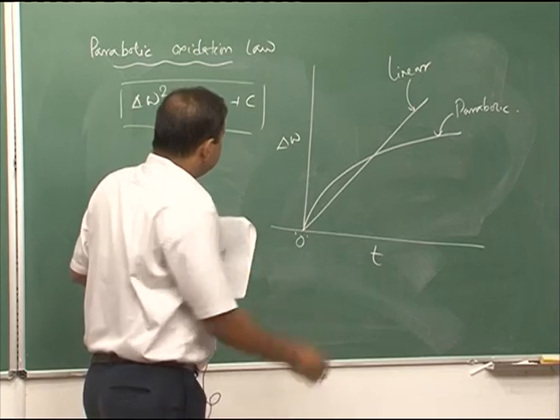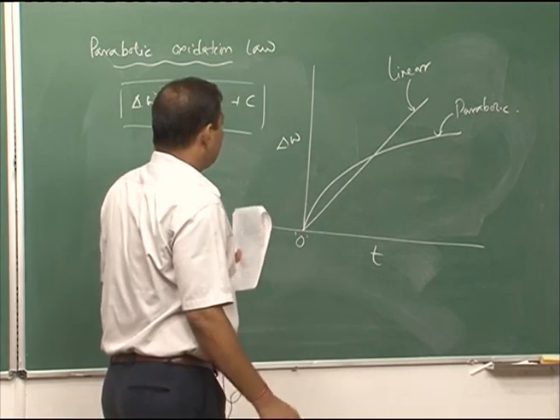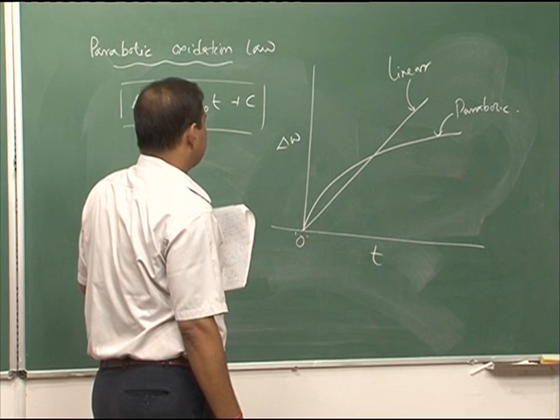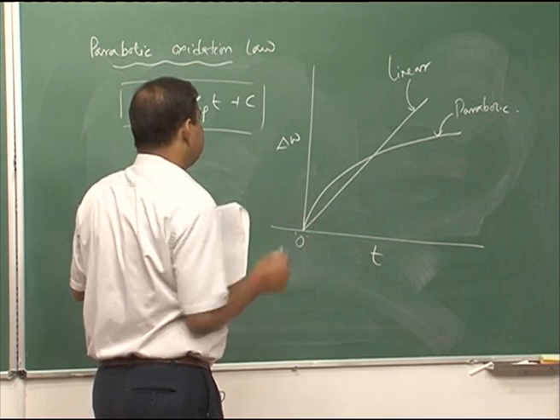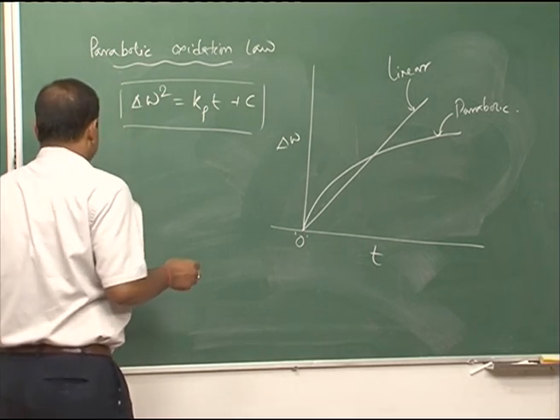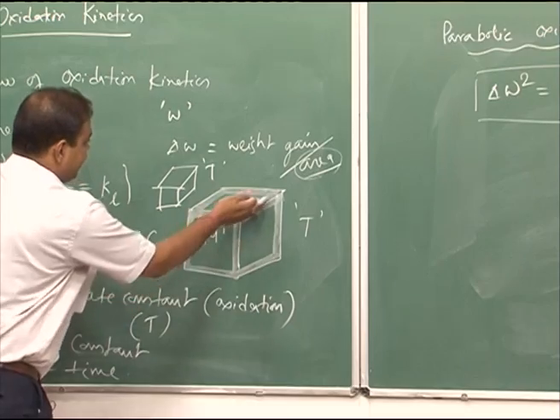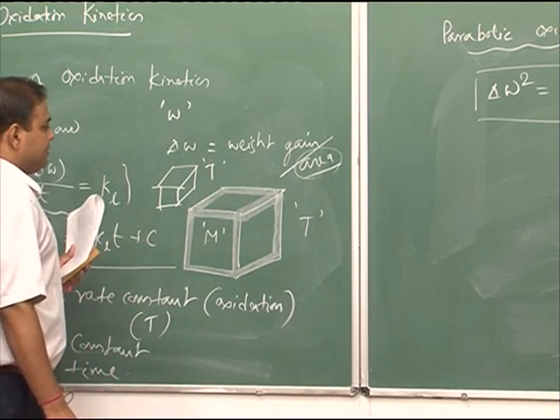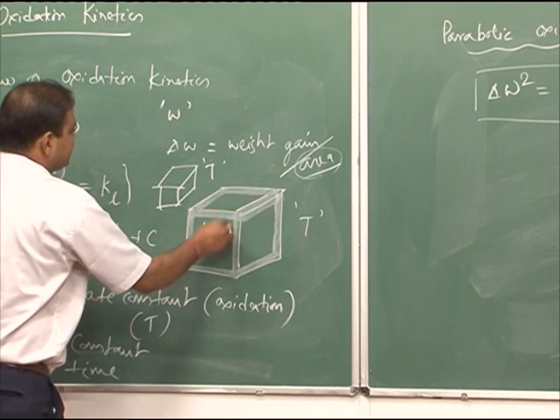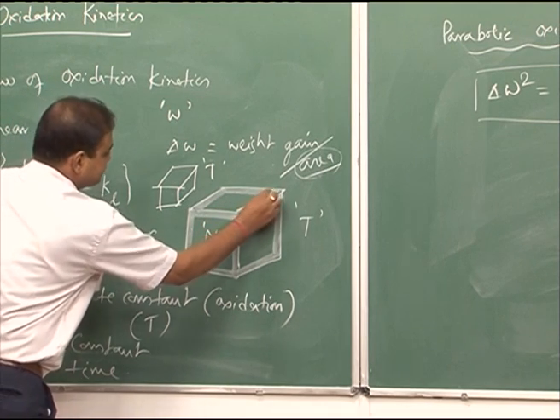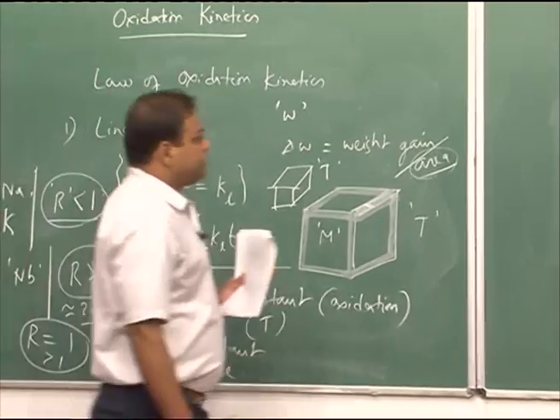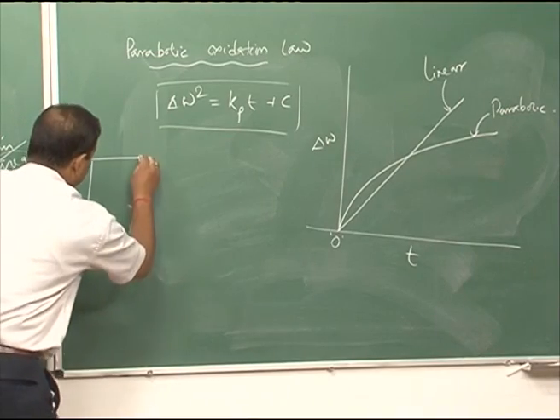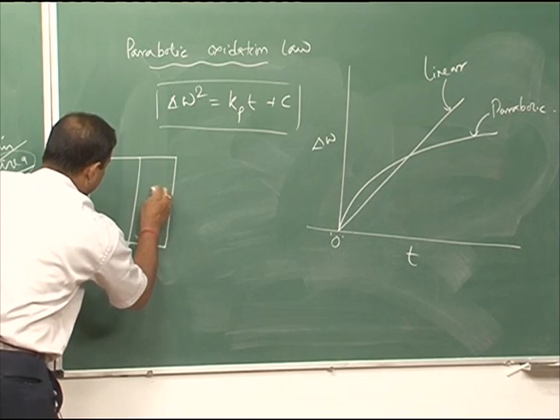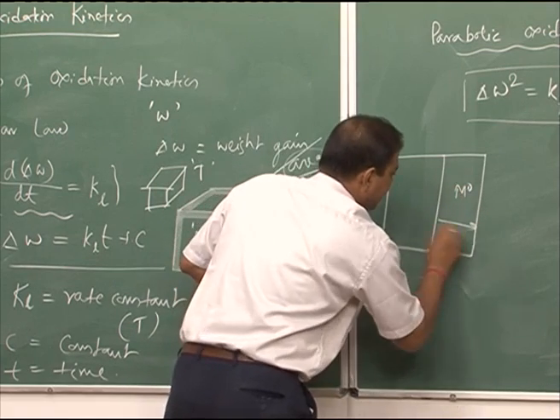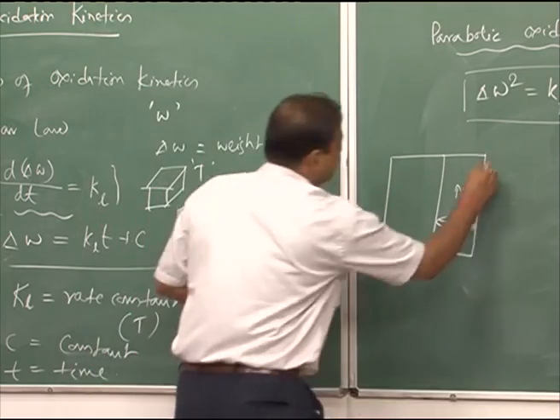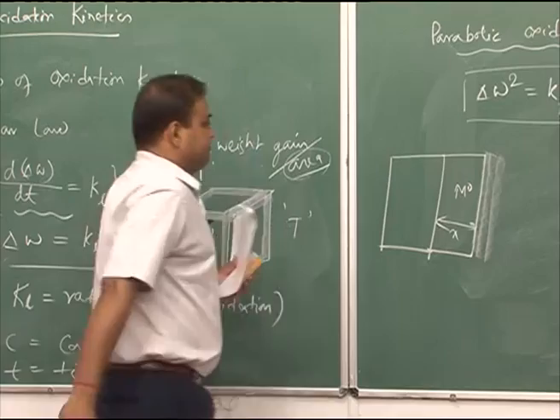Fine. So, that means with the parabolic law, we see a gradual decrease in the rate of oxidation as the weight gain is increasing. Or the other way around, as the oxidation is progressing, you see a gradual increase in the thickness of the oxide layer. So, this is my thickness of the oxide layer. Another way, if we consider this metal, you have the thickness, this is my MO oxide layer. Gradually the oxide layer thickness is increasing.